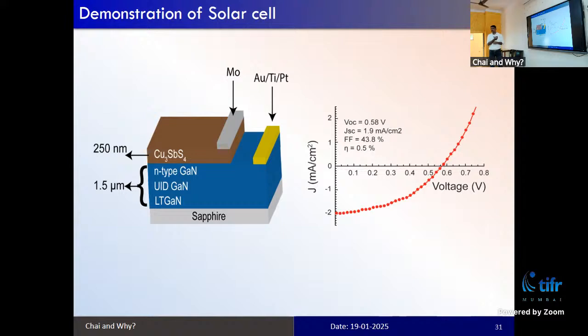But why gallium nitride? This is an intrinsically p-type material, so you need an n-type material, and we took n-type gallium nitride. We have demonstrated an efficiency of 0.5%, which is, until now, the efficiency of this material. There are other stable phases of this material which have given something around 3.2% efficiency. So the research has just started, and people are exploring how to improve the efficiency of this material.